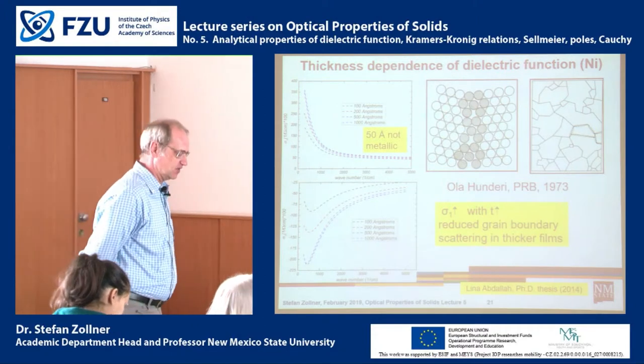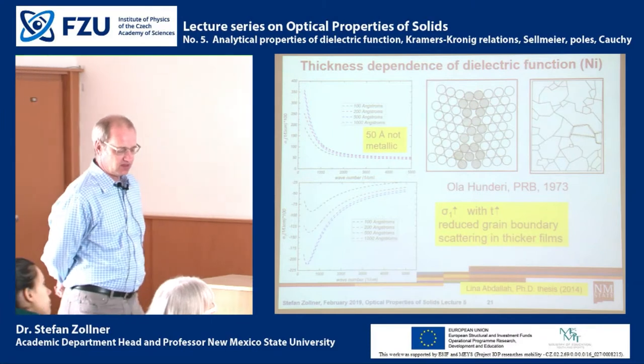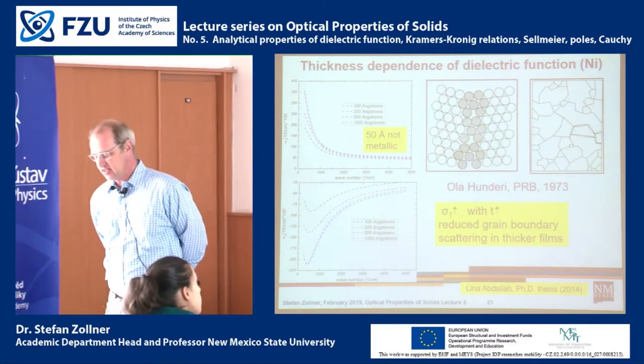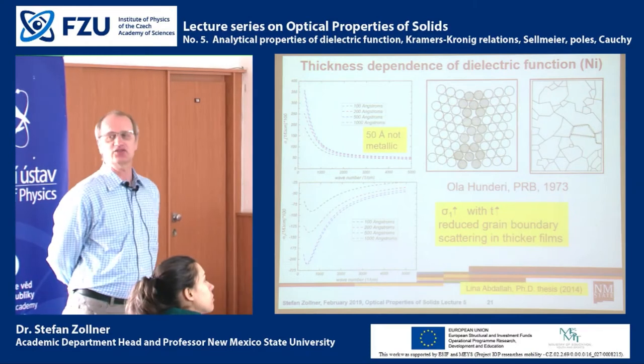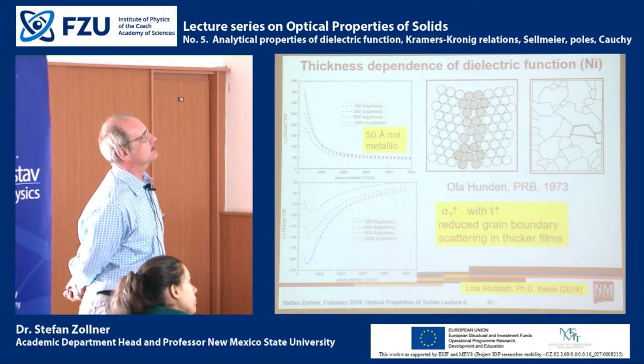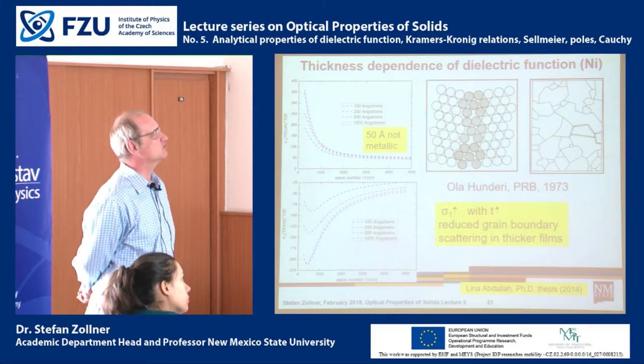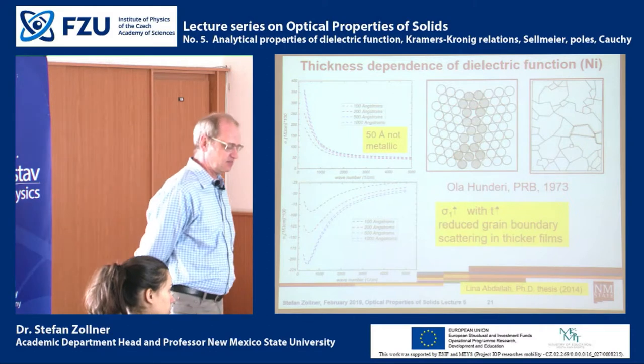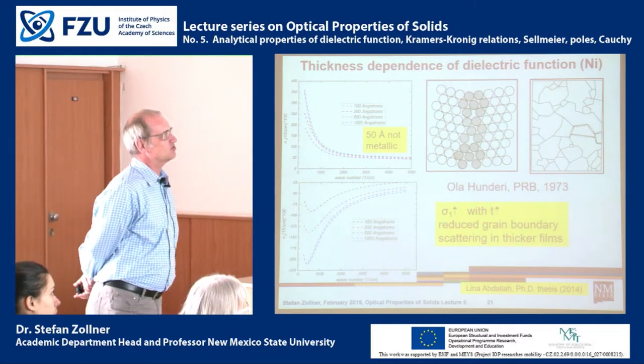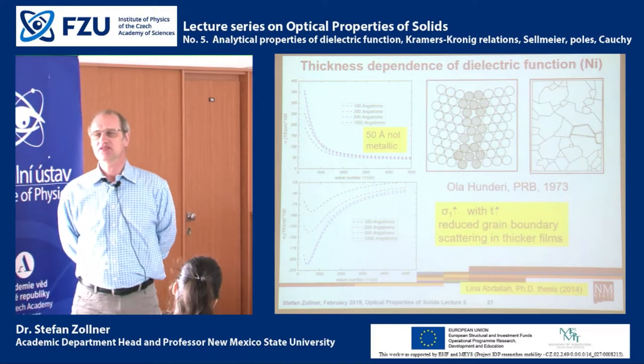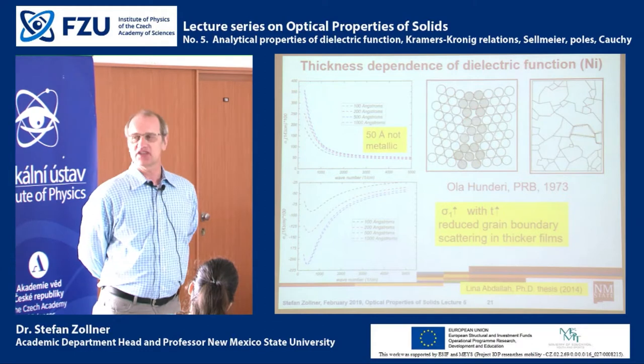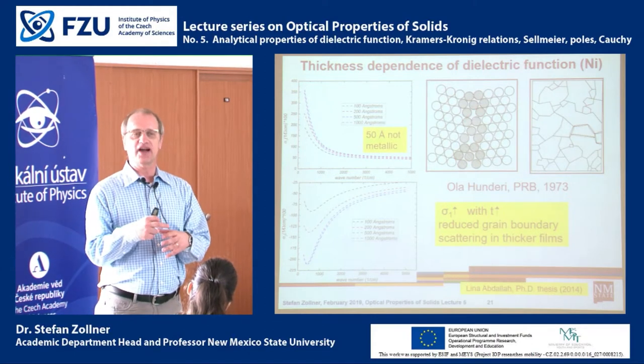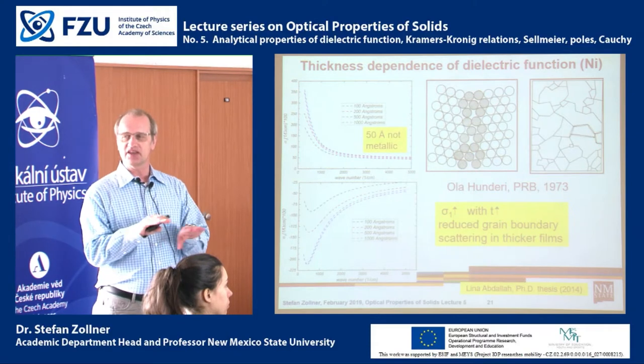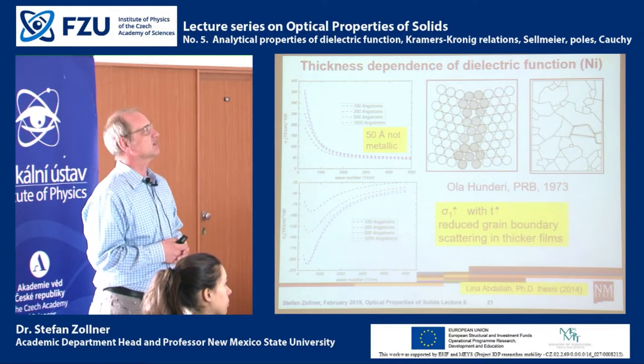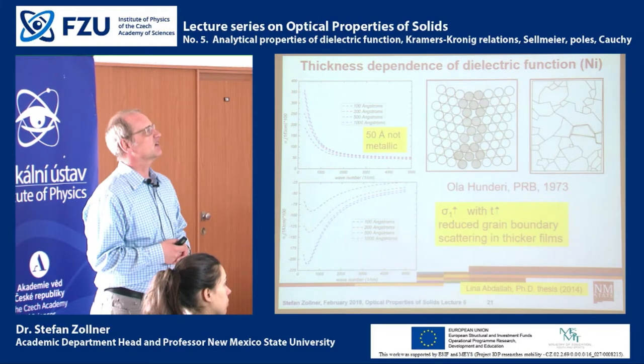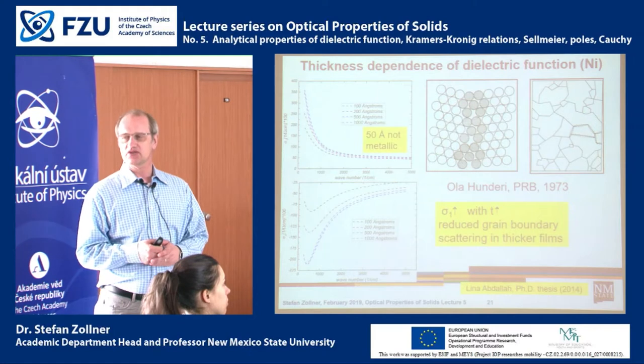So how does the dielectric function of nickel depend on thickness? If you deposit a very, very thin nickel film, let's say 50 angstroms, then depending on the method used to deposit the nickel and depending on the substrate, a 50 angstrom thin film may actually not be a thin film, because there may be surface tension and the nickel may tend to coagulate. So instead of having a uniform film of nickel, you have small islands. You are below what's called the percolation threshold.